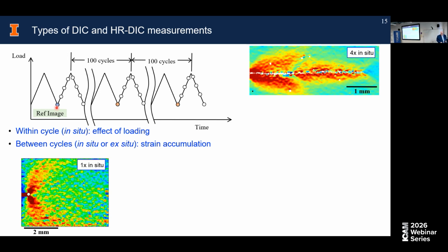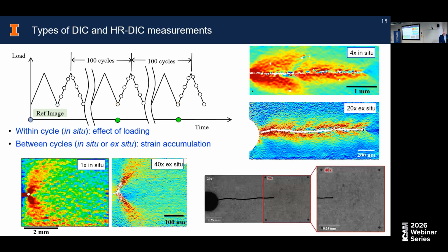And essentially, what you're seeing here is the plastic wake of a fatigue crack. There's been some load shedding that happened here, which is why it gets interrupted. So this would be an in situ experiment between cycles, but we could also remove it or not remove it. We have moved the microscope up to the machine sometimes, and then do this rastering and getting this sort of megapixel image and doing the higher resolution imaging.